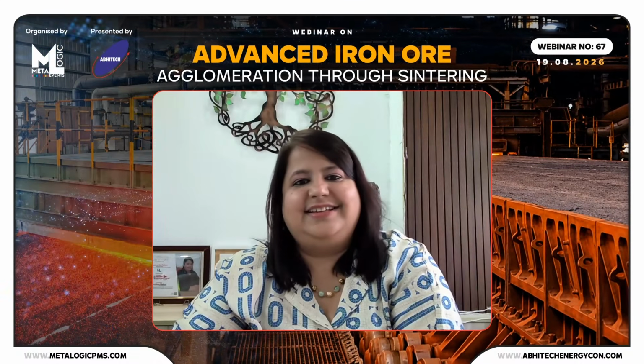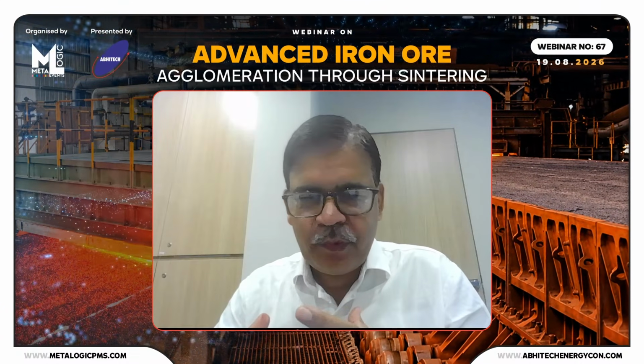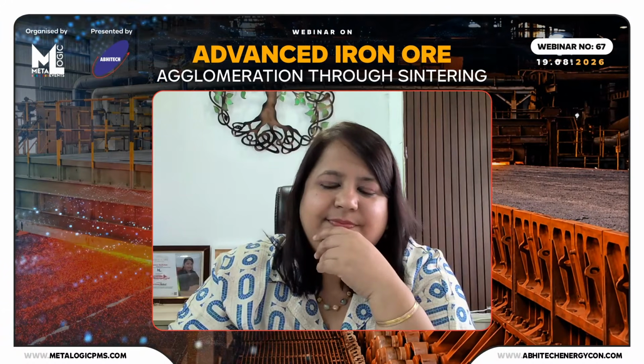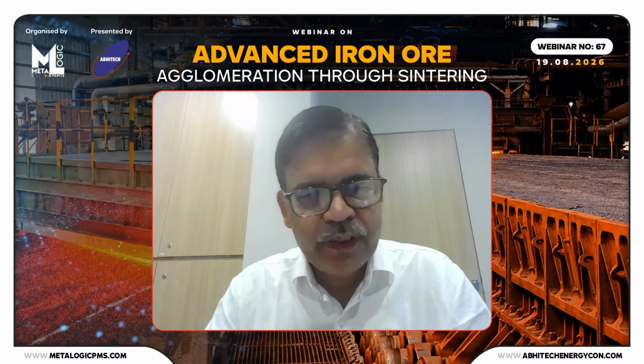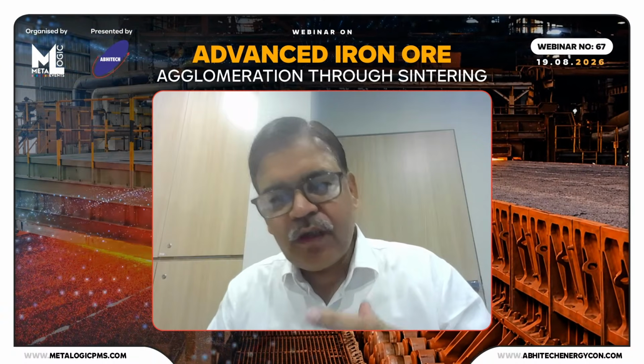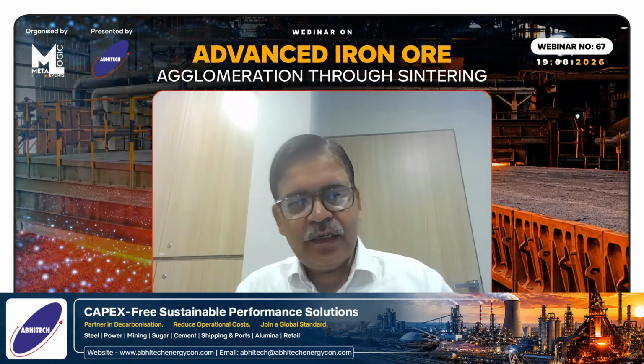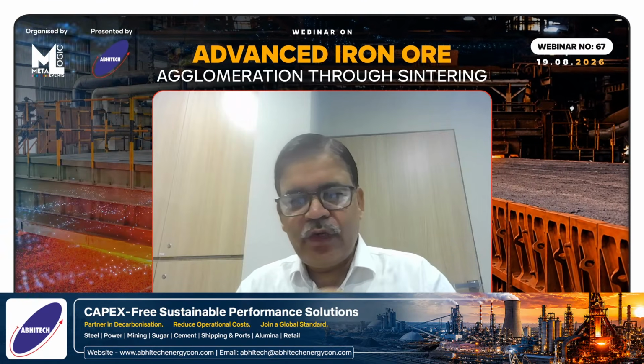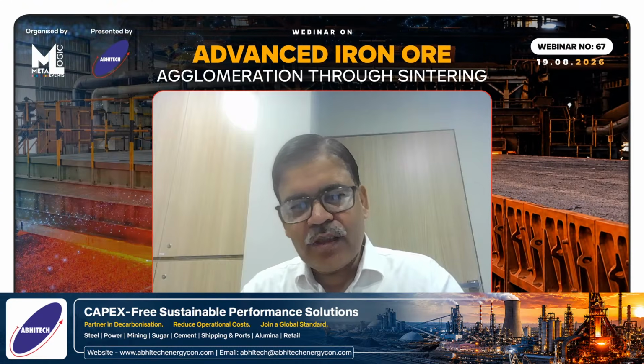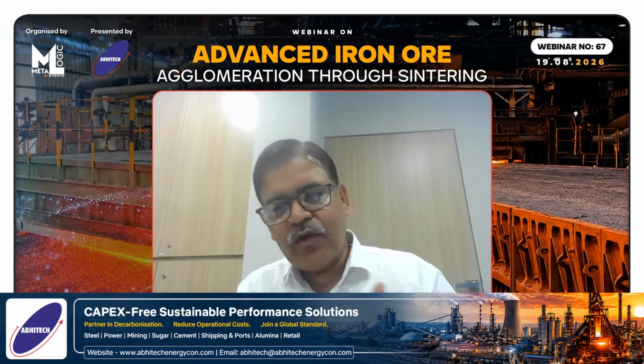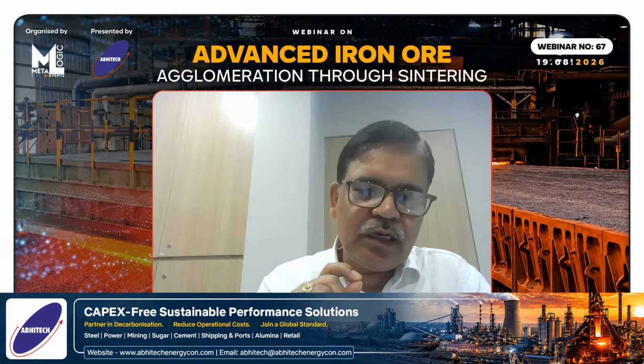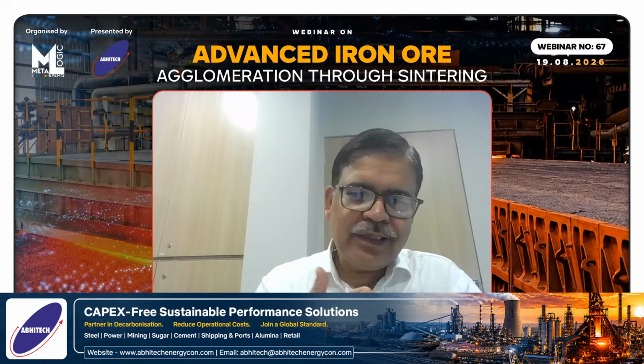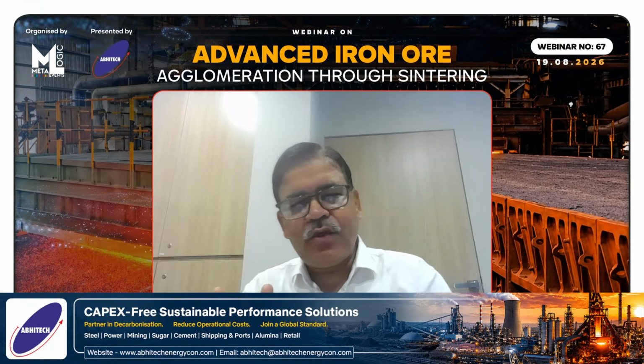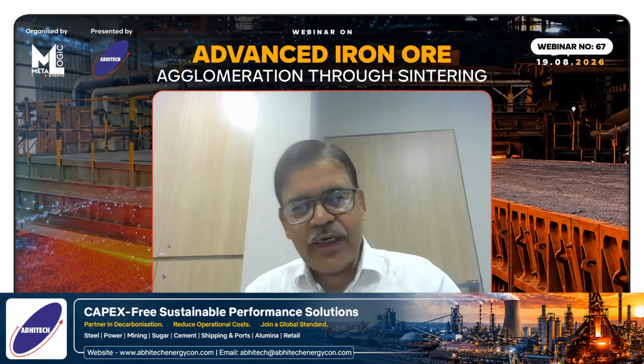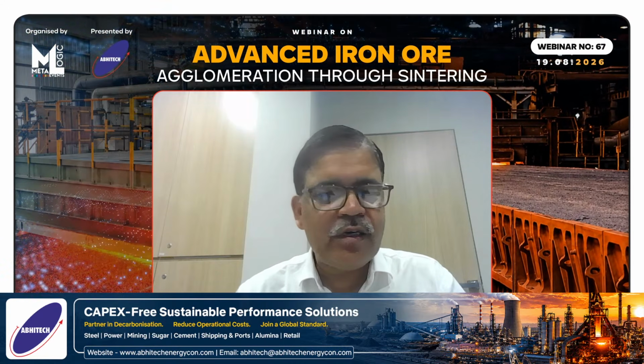Yes. The goethite ore is a kind of weathered hematite ore. So it has more hydroxides, where water is present in the form of crystalline molecules. These are not surface moisture, which can go off when you just heat the material. So it remains with the material, and once it goes into sintering, these crystalline water molecules get released at a temperature of 250 to 800 degrees Celsius. This is basically a kind of LOI, which we call loss on ignition.